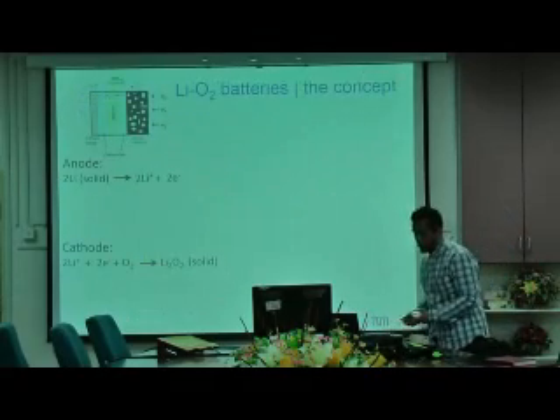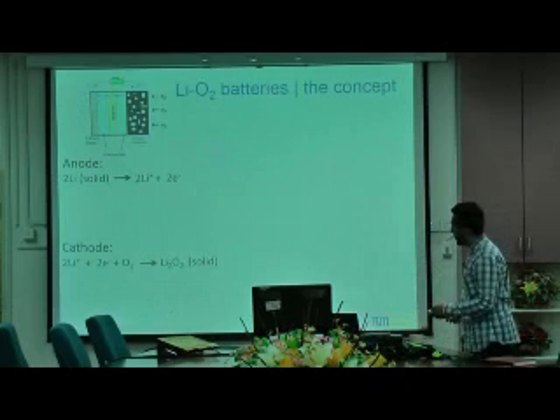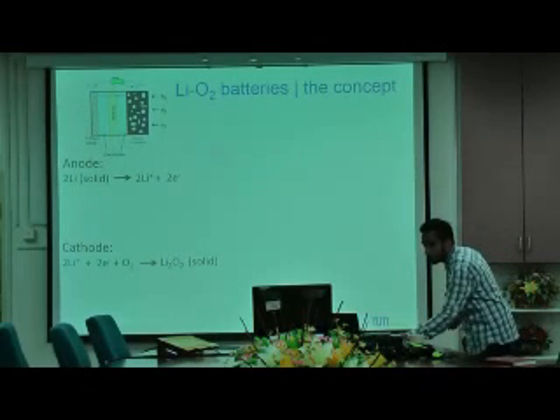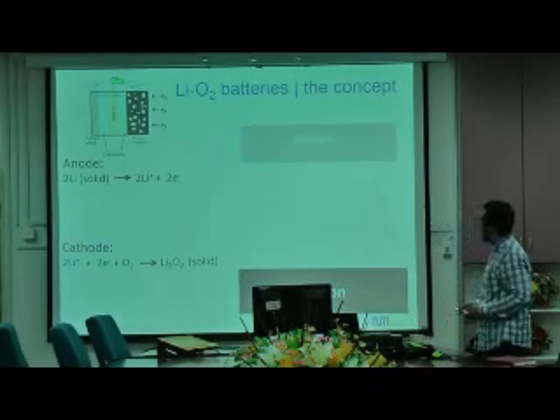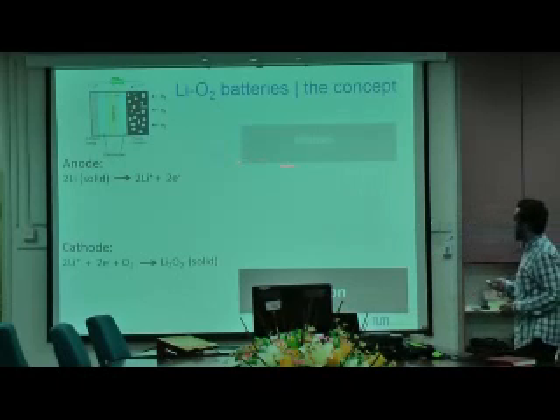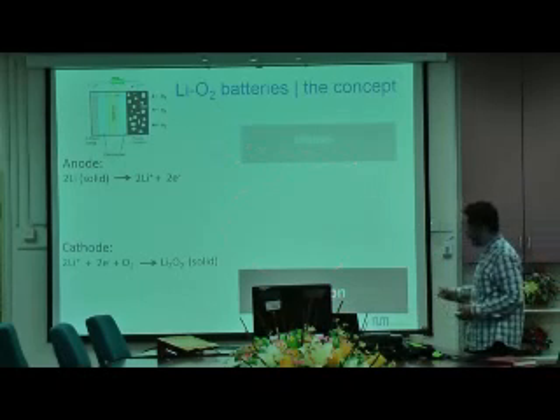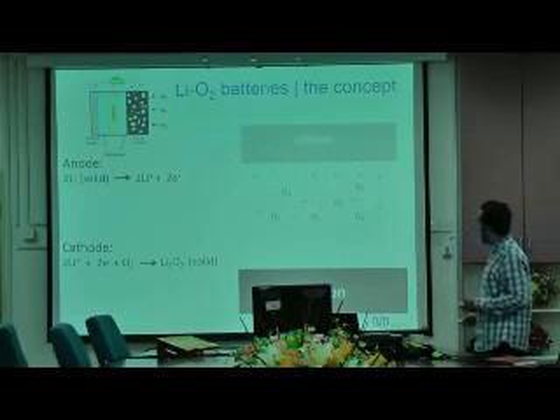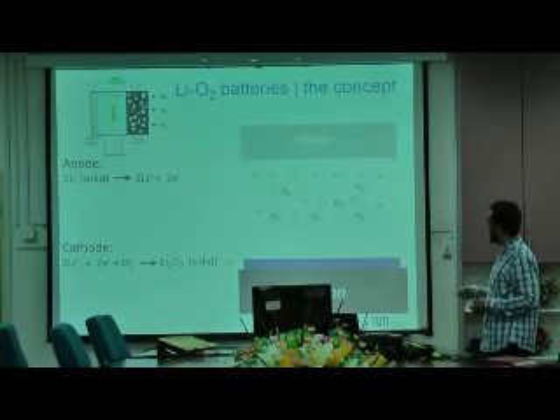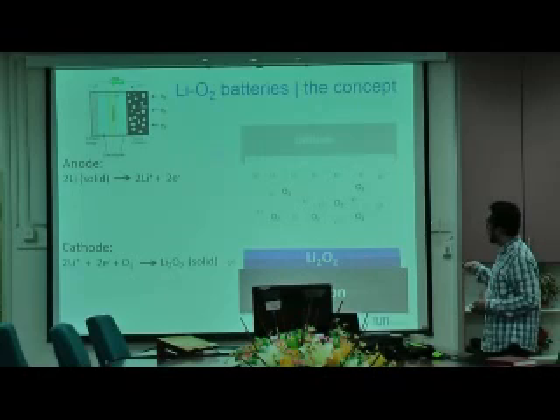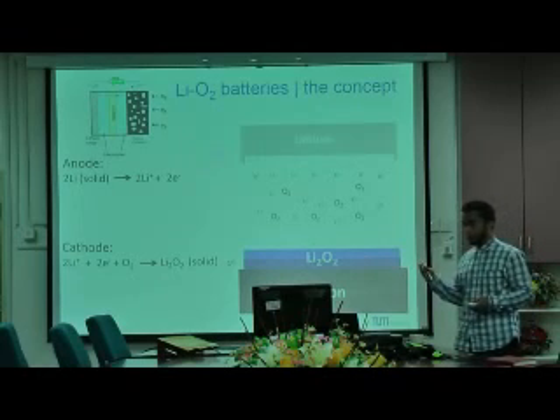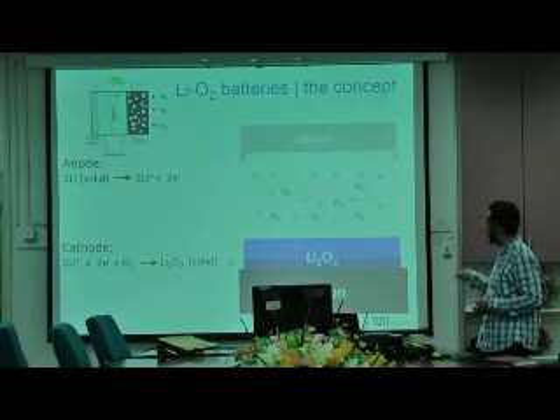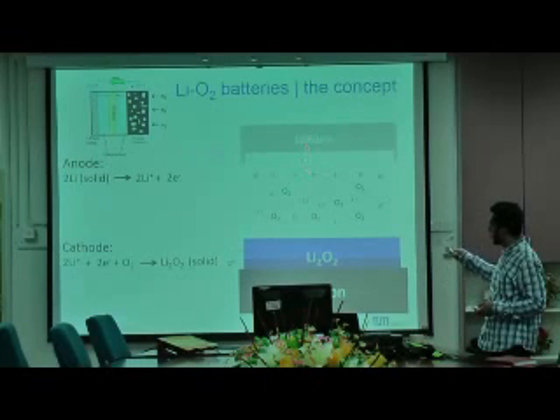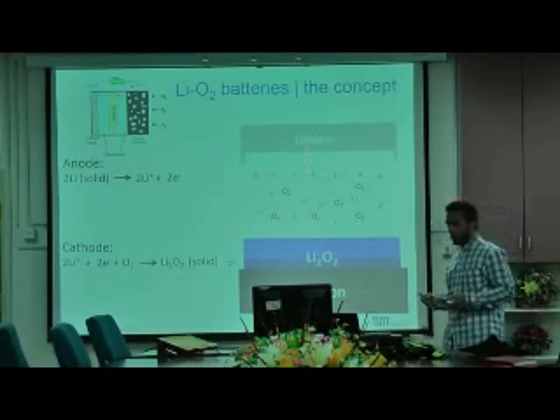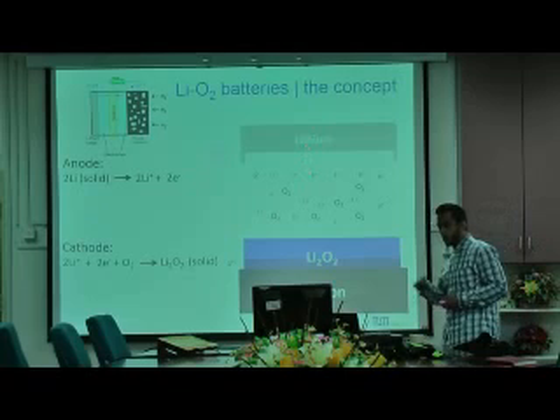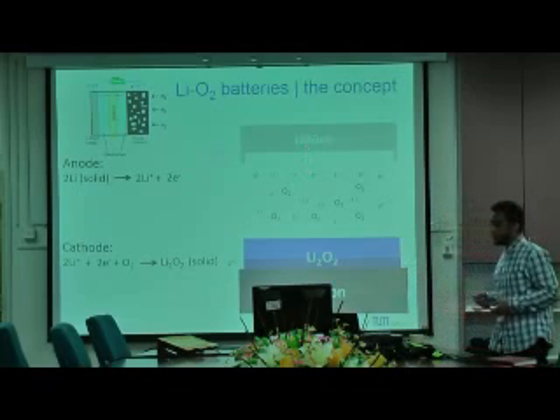So how does this work? During discharge, you have lithium as the anode and carbon as a template for oxygen to be reduced. During the course of the discharge, you start to deposit an oxygen reduction product, lithium forming lithium peroxide. And finally, you need lithium, which, being light and reactive, is one of the highest energy density materials.